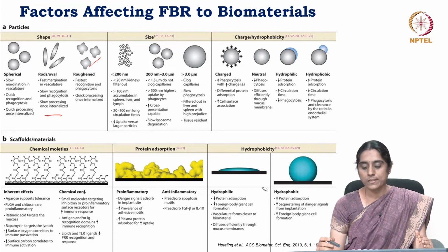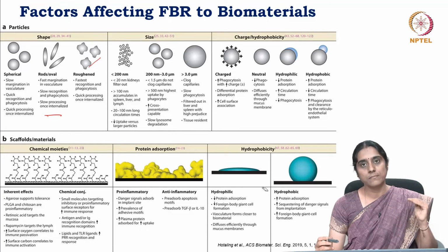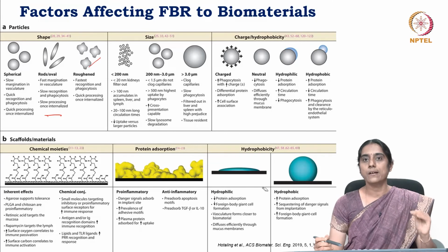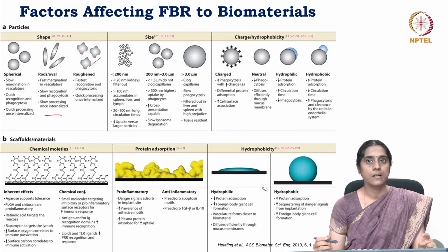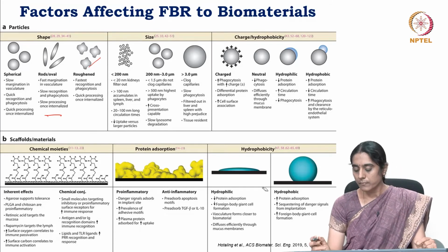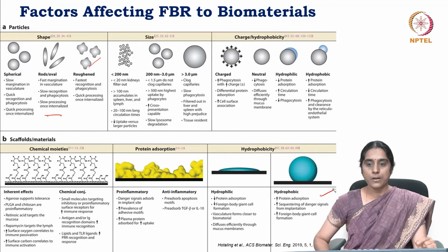Likewise, hydrophobicity also has an influence, high contact angle and low contact angle. So, hydrophilicity causes very less protein adsorption, and it will also decrease foreign body giant cell formation. So, hydrophilicity should be preferred if the foreign body reaction needs to be decreased. Vice versa happens with hydrophobic surfaces.